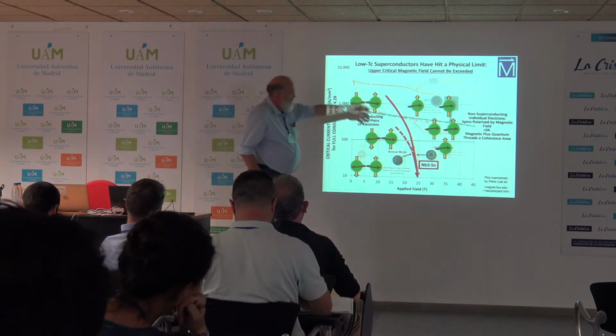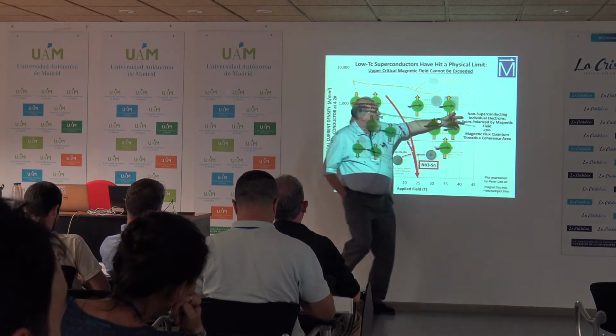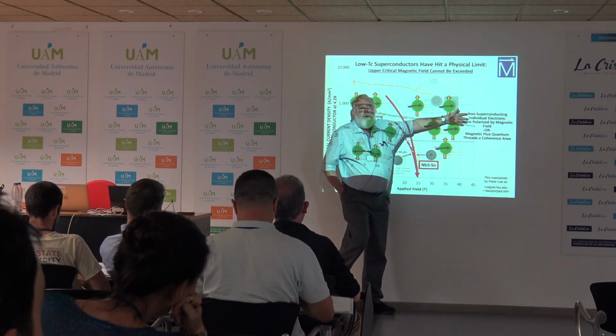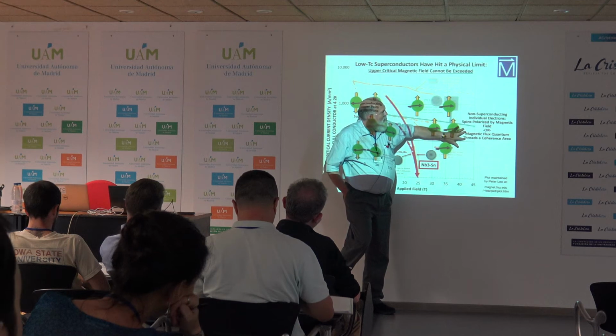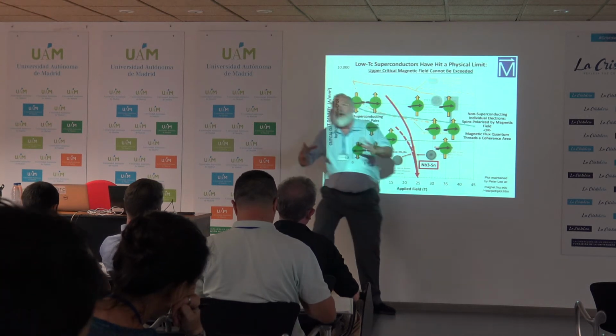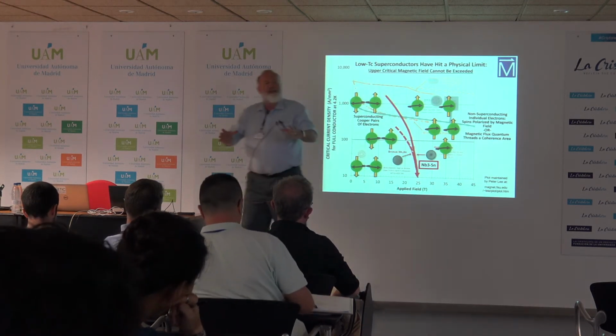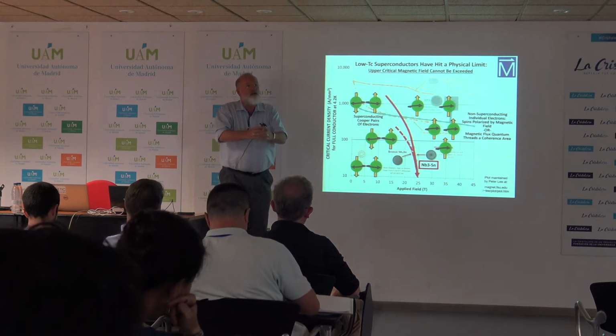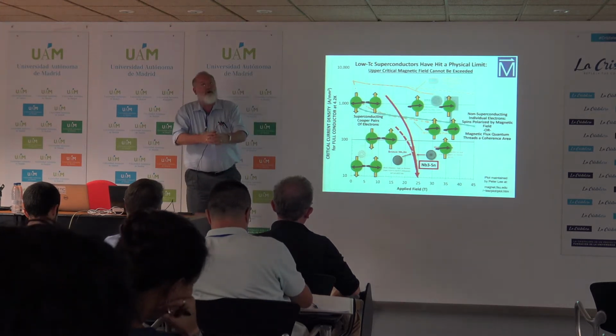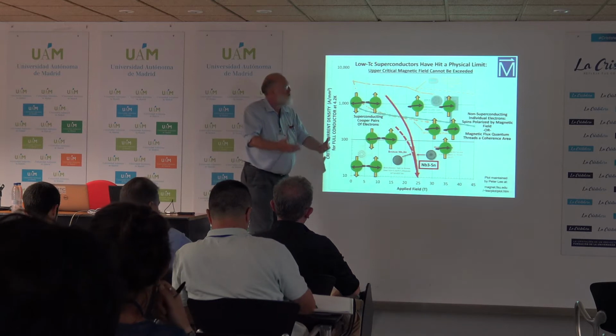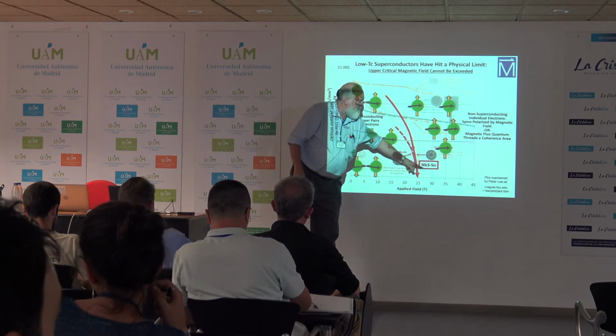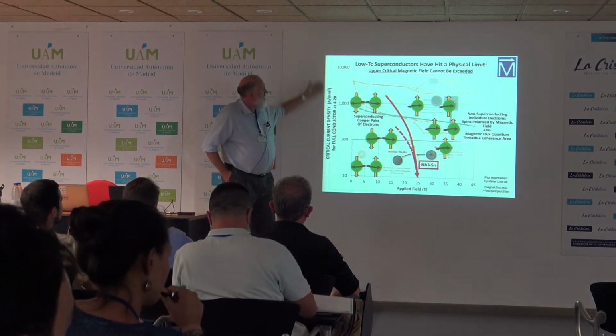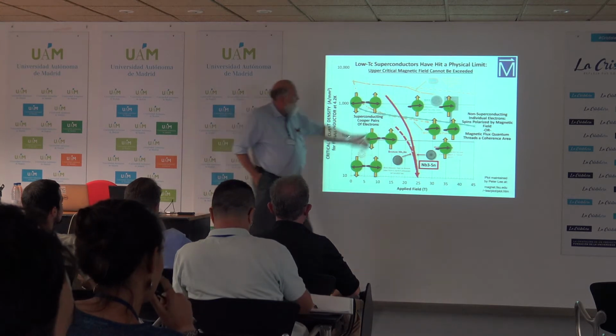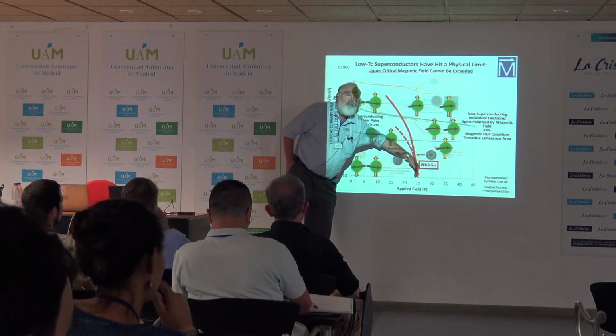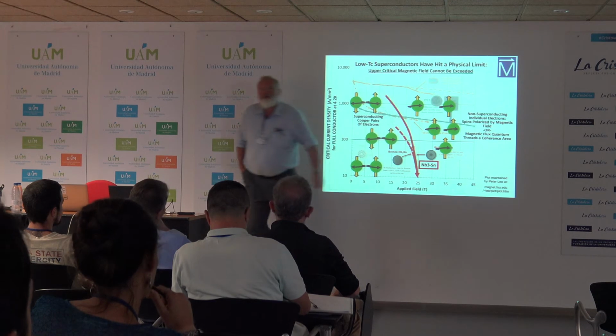One, as I show here schematically, you can spin polarize the individual electrons, the so-called Clogston limit, or a magnetic flux quantum can thread the coherence area. So for high Tcs, you've got a very short coherence length, so a small coherence area, and it takes a huge magnetic field to kill the superconductivity. But notice niobium-3 tin is losing its entire ability to carry critical current, a supercurrent, at about 25 Tesla.